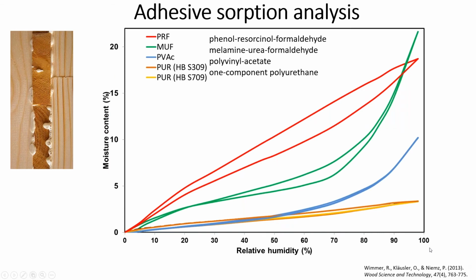In another study, we looked at commercial adhesives that are used a lot in wood gluing, which were phenol resorcinol formaldehyde and melamine urea formaldehyde. Both are used in constructions and also composite materials. And the joiners' glue, the PVA, polyvinyl acetate, and two types of polyurethane. And the same thing, the polyurethane has no hysteresis, and they very little pick up the vapor. Whereas, and that was, I remember, when I was looking at the graph the first time, the PRF are picking up moisture almost like wood, or the MUF.